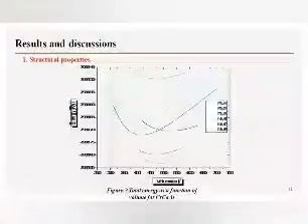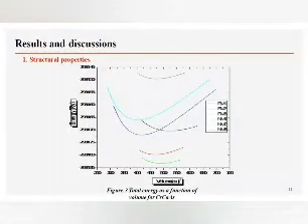Results and discussion. We start with structural properties. In order to obtain the equilibrium lattice constant of the studied half-Heusler alloys, we have firstly calculated the total energy as a function of the cell volume per formula unit in the ferromagnetic and non-magnetic configurations for each possible atomic arrangement type 1, type 2, and type 3. The optimization graphs are presented in Figure 3.